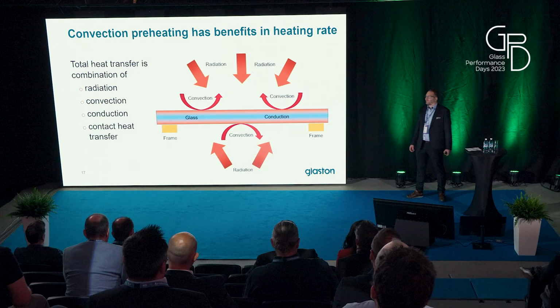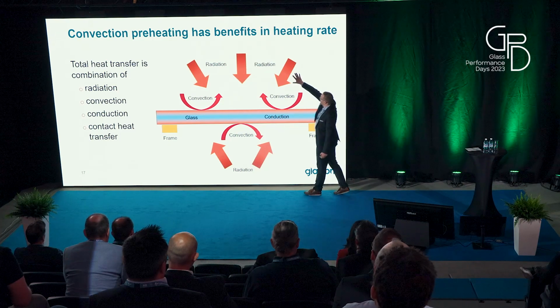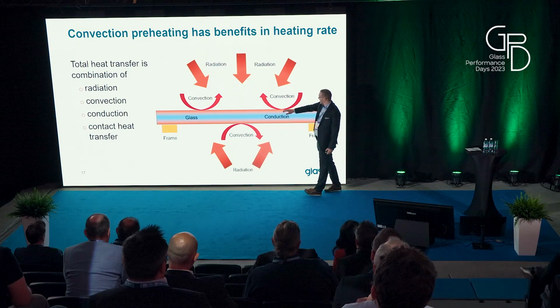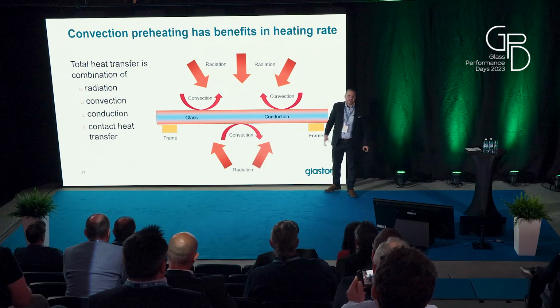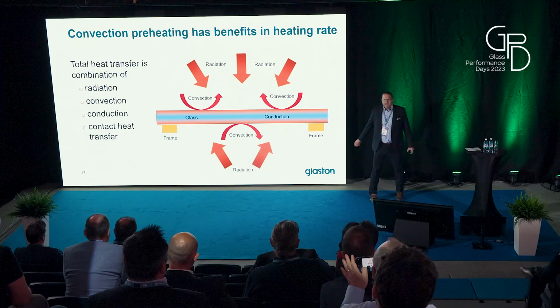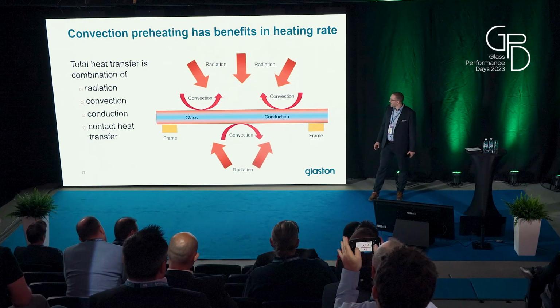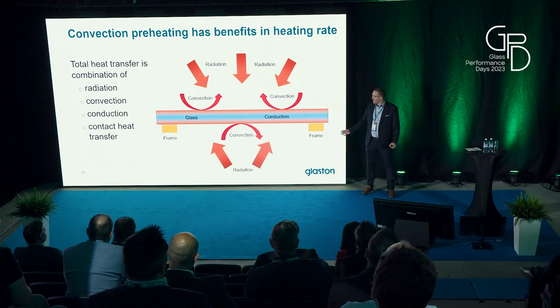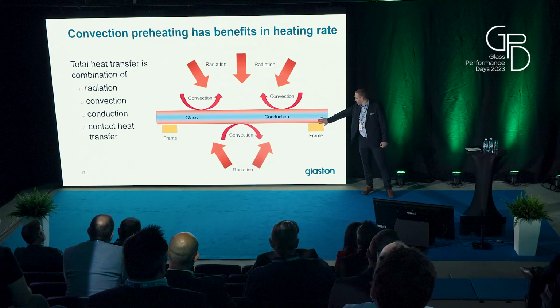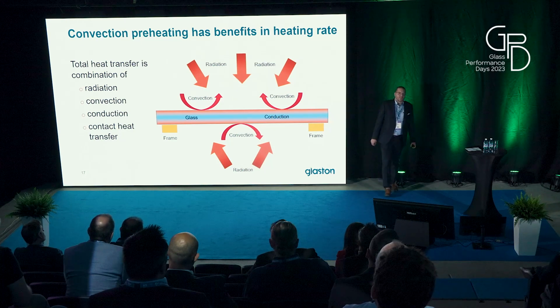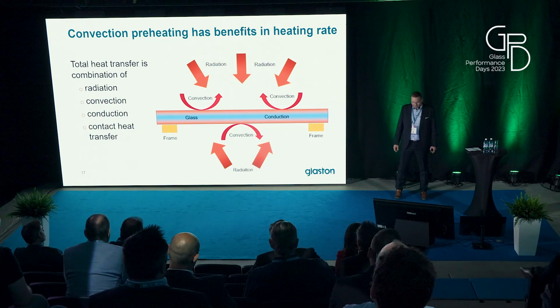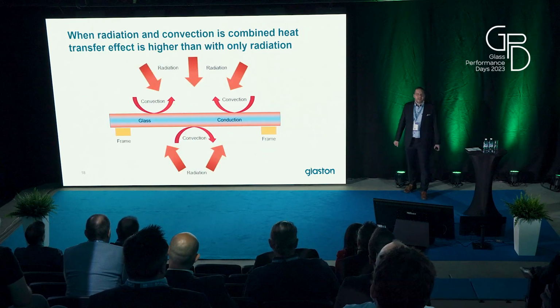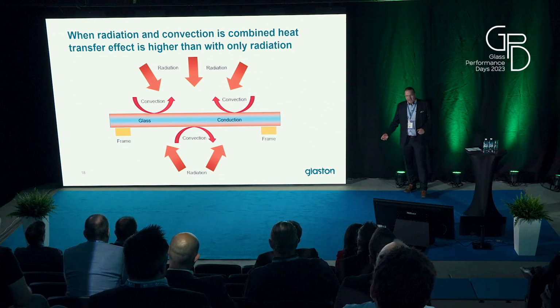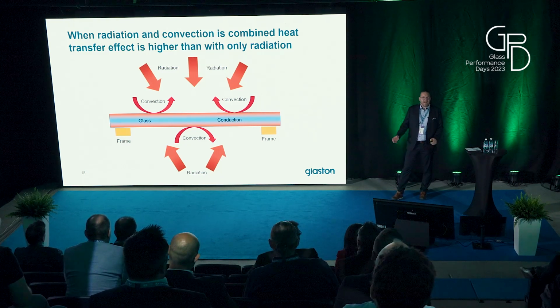Total heat transfer is a combination of radiation, which is coming from heaters and surfaces to the glass surface. Convection is heat transfer that happens between the surrounding air and the glass surface. Then conduction is what happens in the glass, and contact heat transfer is what happens between contact points between the frame and the glass surface. And we can say that by combining convection with radiation, we can increase the total heating effect.